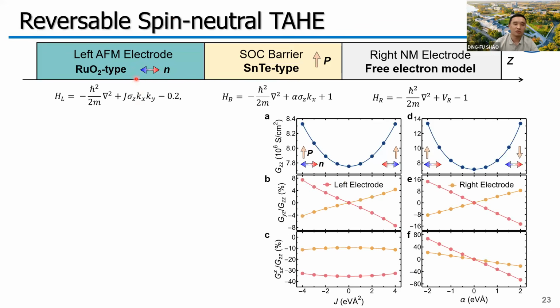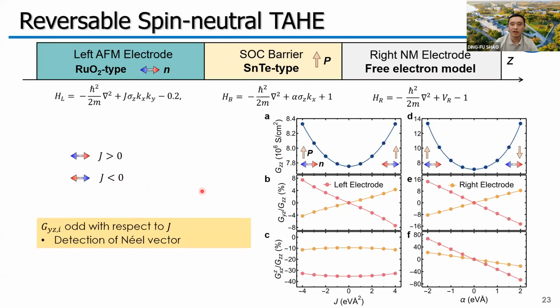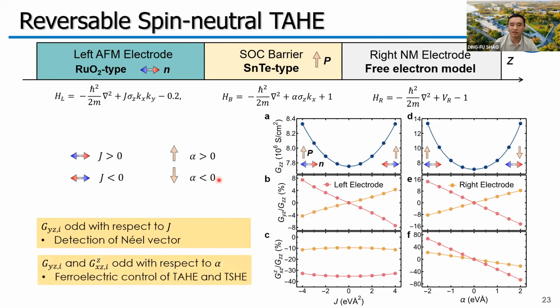Since the switching of the Néel vector will also switch the spins on the Fermi surface for ruthenium oxide, in order to simulate this, we change J from positive to negative and find the tunneling anomalous Hall effect is an odd function of J, which means we can use the tunneling anomalous Hall effect to detect the Néel vector. And since tin telluride is a ferroelectric material, the switching of ferroelectric polarization can switch the spin texture on the barrier. So we change alpha from positive to negative, and found that both effects are odd functions of alpha, which means we can use the ferroelectric switching to control these effects. This will open new opportunities to design voltage-controlled spintronic devices.